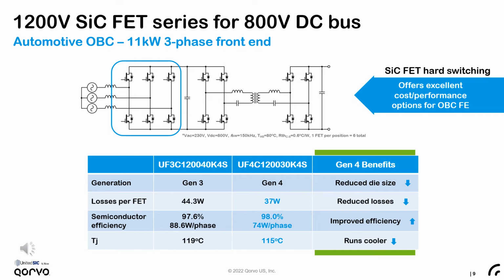The FETjet calculator can be found at our website at www.unitedsic.com, and it's preloaded with the new Gen 4 1200 volt FETs. Here you can see the excellent semiconductor efficiency of 98%, with a loss of approximately 37 watts per FET. And this is when switched at 150 kilohertz, allowing for improved power density. The anticipated temperature rise is a very manageable junction temperature of 115 degrees C.